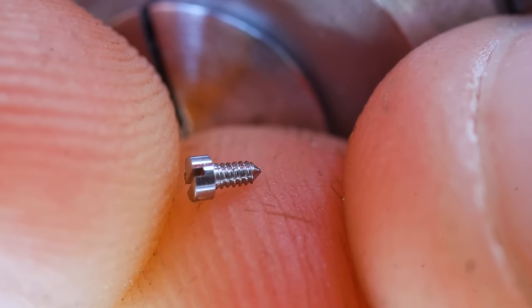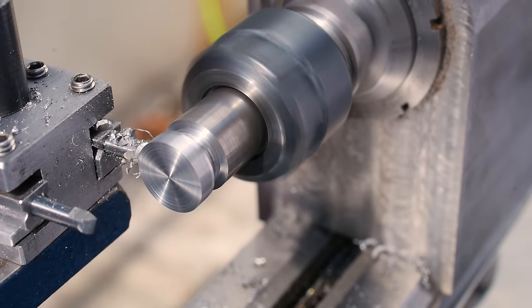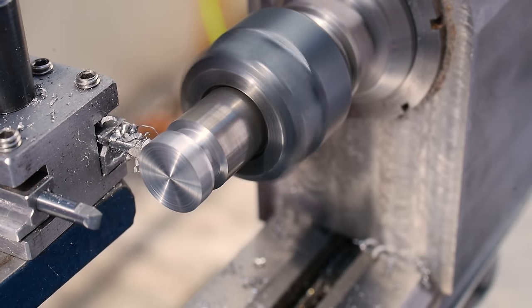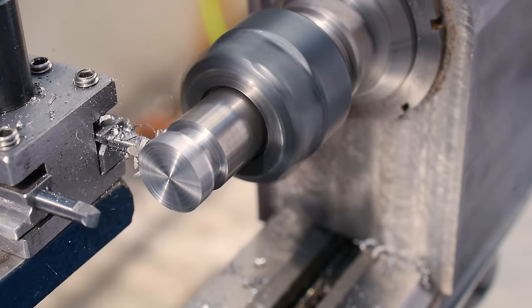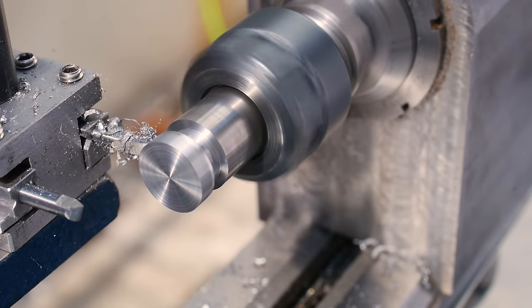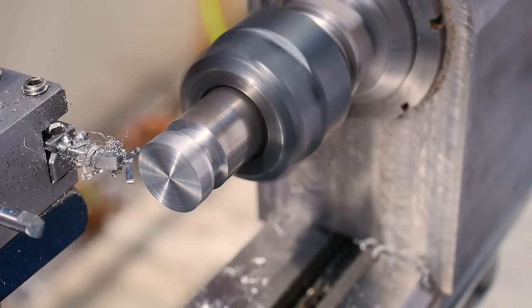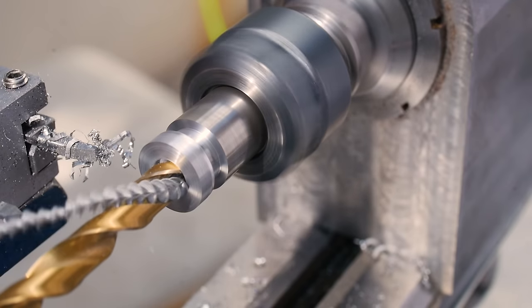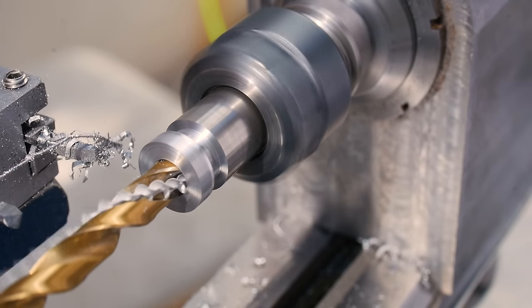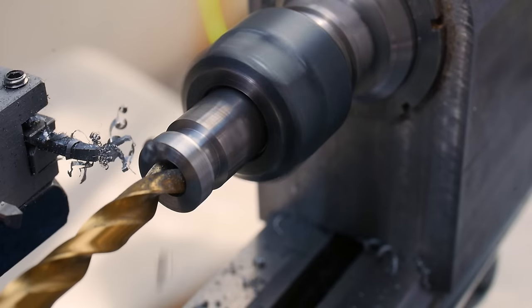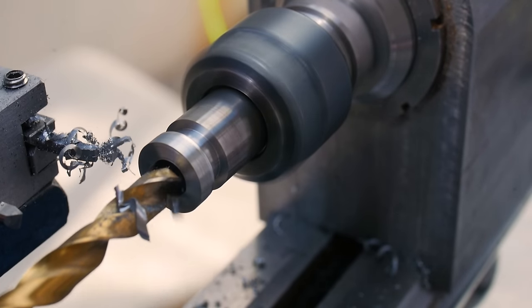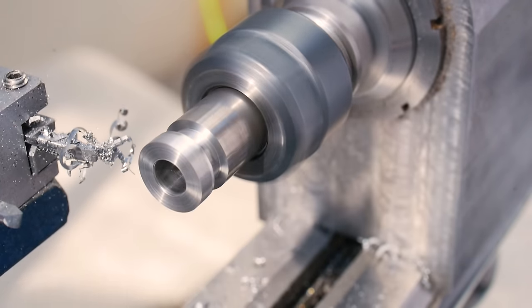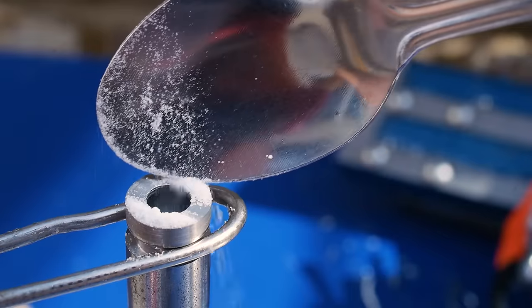Watch screws are made from a high carbon steel, which allows us to change the microstructure of the material to a martensitic phase. Practically, this means that when I heat it up enough, and cool it down quickly enough, the steel hardens, and as a result, the screw is stronger. However, when I heat it up enough, the surface of the screw will oxidize, which is undesirable.